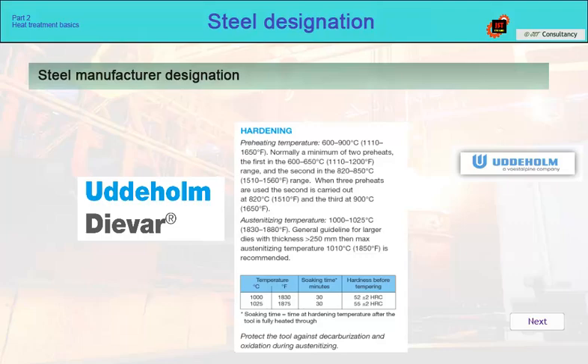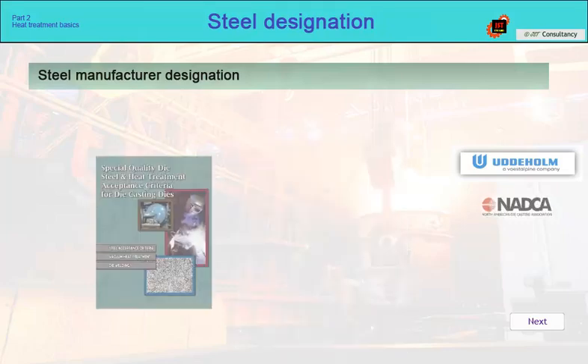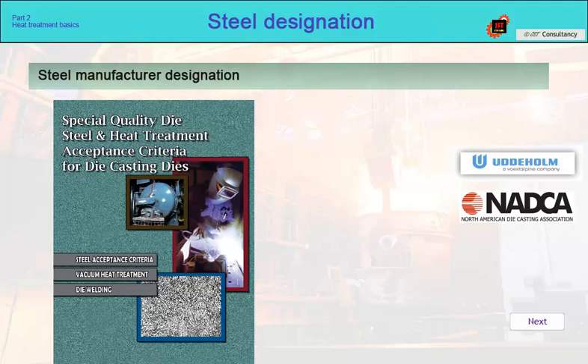However, if the steel is intended for die casting dies, then this does not apply either, because both the tool manufacturer and the heat treater must proceed strictly according to NADCA 207, which is the North American Die Casting Association specification for the production of die casting dies. At the same time, it is necessary to take into account the recommendations according to CQI 27, Casting System Assessment, for die casting parts for the automotive industry.